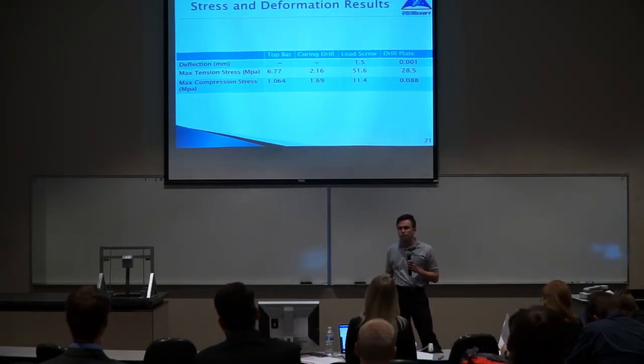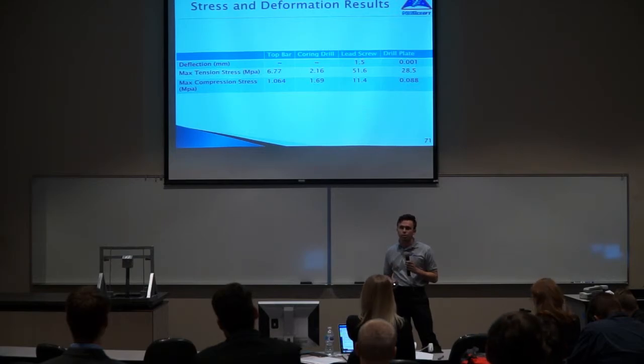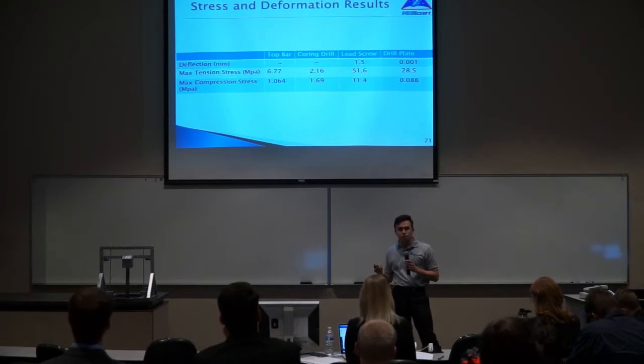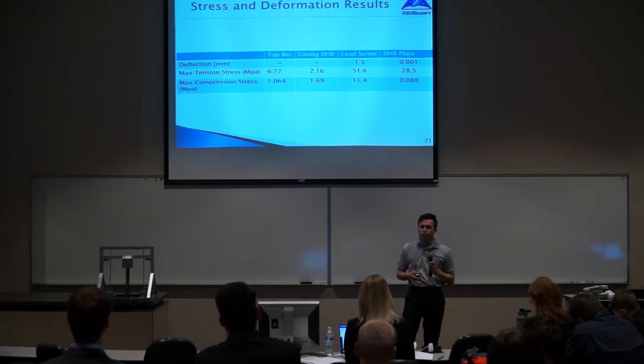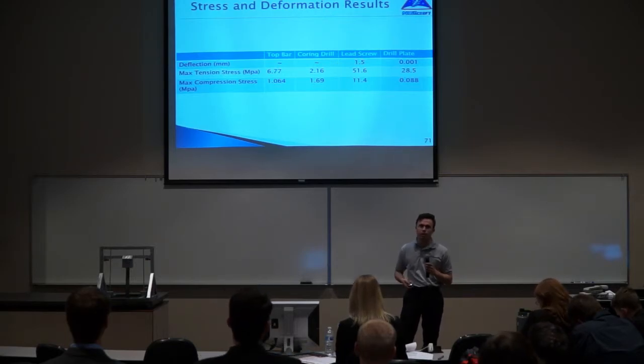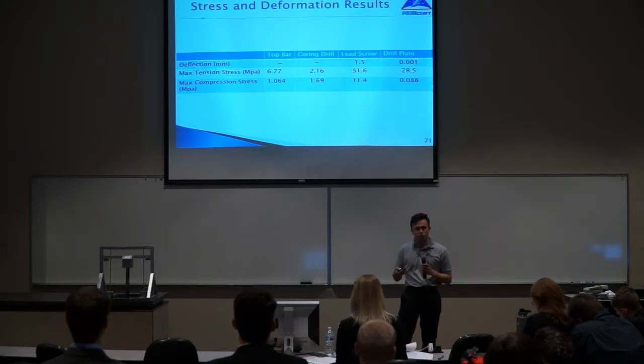So the greatest stress that any one of these components encounters is actually in the lead screw, which is 51.6 megapascals. As far as the compression stress is considered, we only encounter something around 1.69 megapascals. So as far as the test pass criteria is considered, we have passed all of this criteria. Future work, I would like to simulate the thermal stresses.